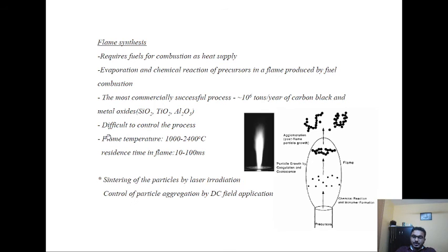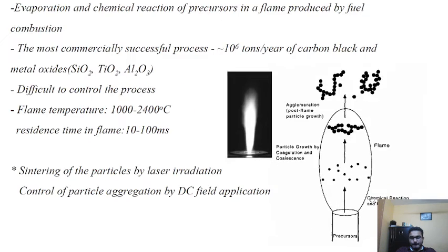It is difficult to control, and the flame temperature is up to 1000 to 2400 degrees Celsius. The residence time in the flame is 10 to 100 milliseconds.